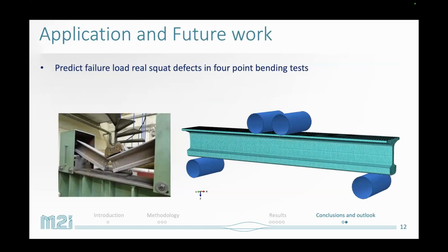And then one last slide, an outlook, a bit of a look forward. So as you saw in the first slide, we had this squat defect from practice, which was broken in the 4-point bending test. And the final goal is now to recalculate the fracture load of this 4-point bending test, including the real squat geometry. So I'm using a 3D scan to model that, and I made a finite element model of this test. And in the end, we're going to expand it to calculate the residual fatigue life of squat defects.